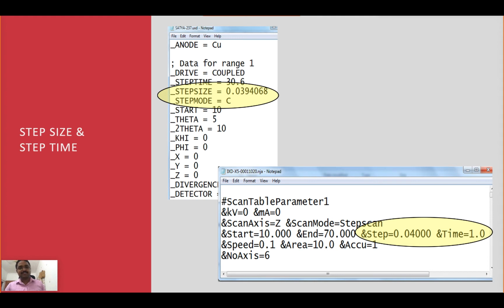If you are going to reduce this, what will happen? For example, if you are getting 1000 points with this step size of 0.04, and I reduce it to half, 0.02, then the number of points obtained in your data will be 2000. For step size 0.04 it is 1000, then for 0.02 it is 2000. So in this way you can improve the statistics. What I mean by statistics is the smoothness of the curve, validity of the data, so everything will improve.